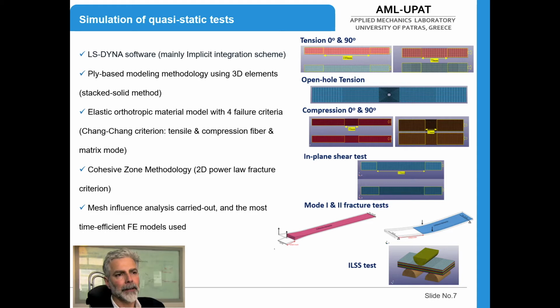For the interlaminar fracture properties, cohesive zone methodology was used. The basic advantage of the cohesive zone model method is that the locus and direction of a crack initiation do not need to be predefined. Then, in the case of impact, which is the final application of the current work, the locus of damage initiation is not obvious. During this work, the convergence test was very precisely checked, and the mesh influence analysis was carried out in such a way that time-efficient FEM models were developed.